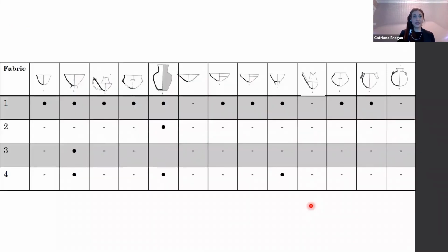And once again, when we try to identify forms, the most common fabric, which makes sense because most of our samples relate to it, seems to have been used across a wide range of forms, so we see a lot of different vessels produced from this material. Then the other two fine wares were a bit more limited in what they could tell us. Basically fabric 2 is associated with this jar, whereas fabric 3 is associated with a pedestal bowl.